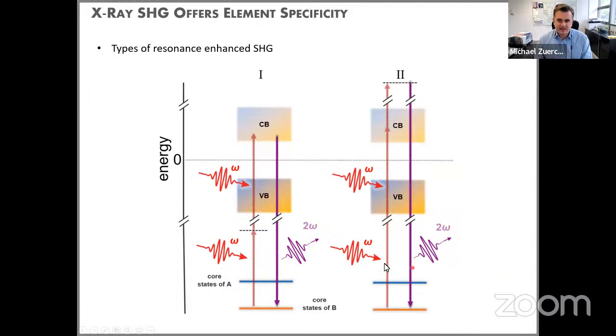from these states. In this case, you would observe the second harmonic at twice the energy of the linear X-ray absorption edge. We have successfully measured in both of these situations, and I will show you examples. I just wanted to bring this up early so that you're all aware of the different energy schemes and why we use certain free electron laser energies in certain circumstances, which I will show later in the talk. This gives us some leverage to plan the experiments and use different selection rules, for example, to excite and measure different symmetry states in the system.